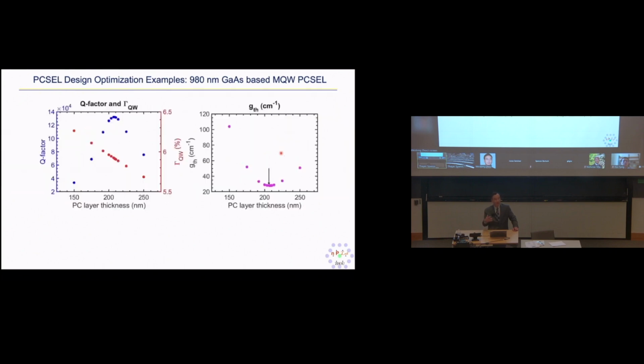And then finally, based on some detailed calculation, we can estimate the quality factor of the cavity resonance. You can see here this blue one, and also the confinement factor, for example, in this case, the quantum well, the overlap of the field with the quantum well structure. Higher is always better, right? But you have to balance between the quantum well and the photonic crystal cavity.